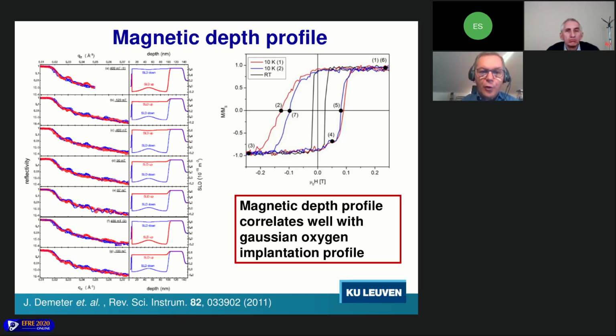And what you see here in this column is the so-called scattering length density. You can say that is a reproduction of the magnetization depth profile in the layer. You see here that we have this sort of Gaussian distribution of the scattering length density, and this fits really very well to the data. So what we see here is that in the end, the magnetic depth profile really correlates well with the Gaussian oxygen implantation profile. So by doing the material modification with the ion beam, at the same time, you are in fact modifying the magnetic properties.